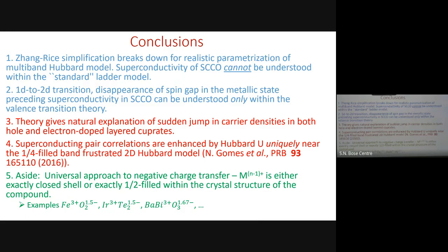I'll tell you one other thing. The spin models. In the spin model, everybody jumped into a straight disappearance of superconductivity with zinc doping. With 3% zinc doping, it disappears. So all the spin people jumped in. Yes, copper 2 plus has spin, zinc 2 plus doesn't have spin. Of course, superconductivity disappears. Now I explain it in the electron doped case. I went to Arizona, got some experimental results saying, do the electron doped case. Superconductivity will disappear at the same concentration. Copper 1 plus is what you are creating. Zinc 2 plus is what you are doping. Both are d10. If the spin models are correct, why would zinc kill superconductivity at the same concentration?